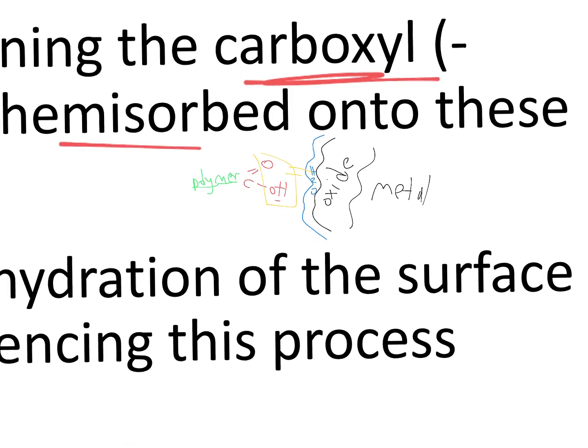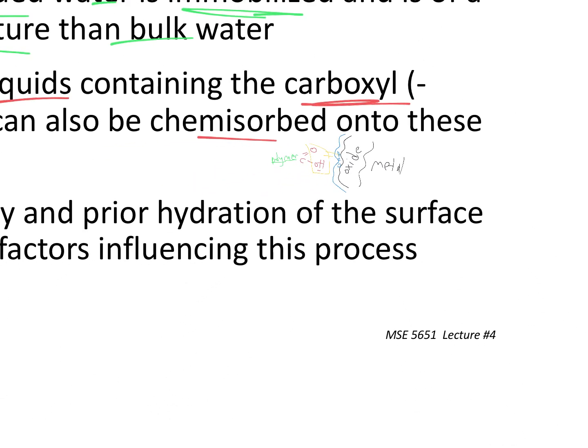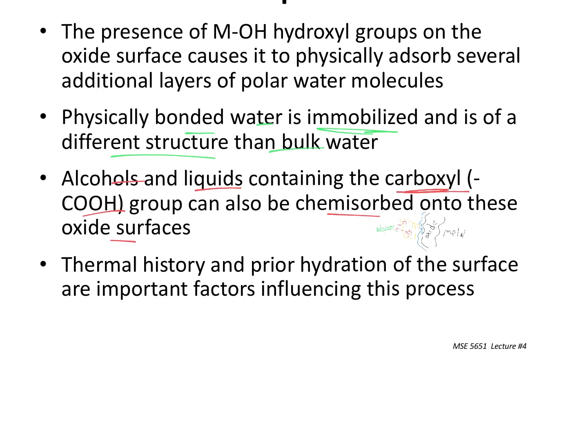And what we do is, rather than just saying whatever, we can engineer a polymer out here. All right, and that polymer can be 100 carbons long. We can make whatever we want, bond to this carboxylate, and then we bond that to the surface of the particles, and now we have a processing additive that controls the behavior of those particles based on this adsorption phenomena. Okay? Does everyone kind of see that? We'll talk more about this, but this is another example of adsorption and why it's so important. Okay, thermal history and prior hydration of the surface are important factors influencing this process and the efficiency of the process as well.